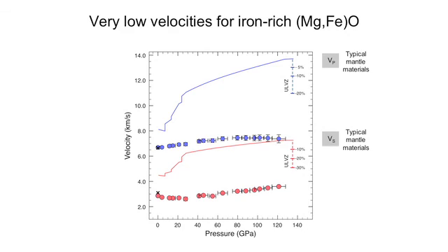And now we can see the same drastic phenomenon in the shear wave in this material. And we see decrements relative to seismic reports of just how low they've observed seismic wave speeds. So if we look at these measurements, they were done without even heating the sample.